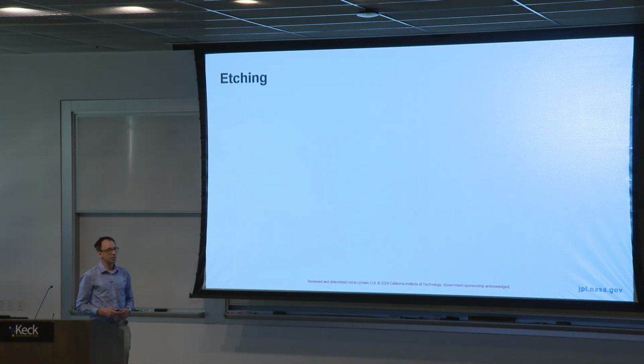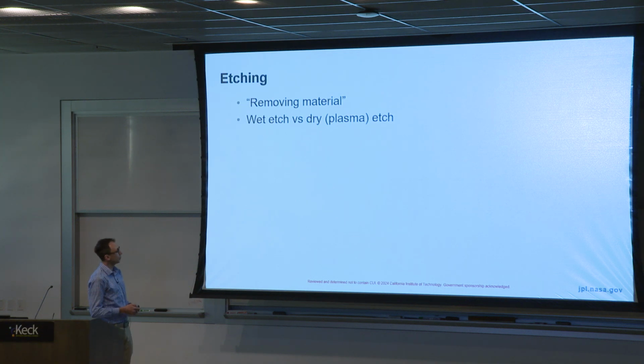Okay, so etching. I think this is quite a big topic as well on its own, not that the others aren't. Essentially what we're talking about now is removing material somehow. The first thing to know about this is that you have two fundamentally different types of etching, often referred to as wet etching or dry, which I'm going to call plasma etching. Wet etching is where you submerge your material or your wafer into a liquid, might be hydrochloric acid, hydrofluoric acid, etc. You depend on the acid to do the work for you, and you don't have very many control parameters. You can dilute the acid, you can maybe heat it up, but that's about it.